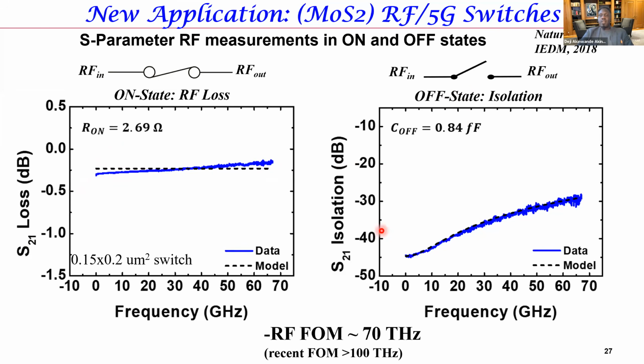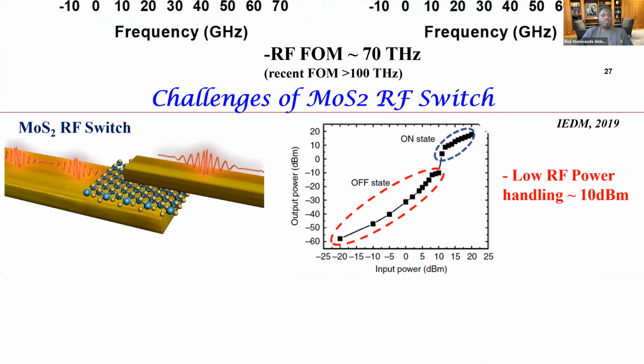Then in the off state, again the same scattering parameters - in this case we call it isolation. You want it to be less than minus 15 dB, and in this case we're around minus 30 dB worst case, so this is very, very good. These are record numbers, even though this is a relatively nascent device.